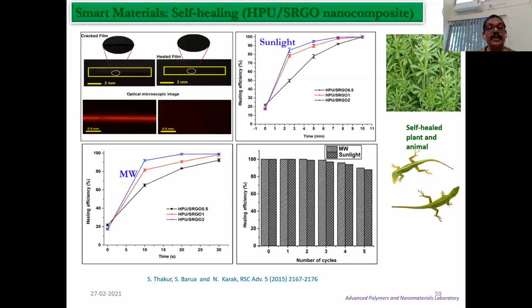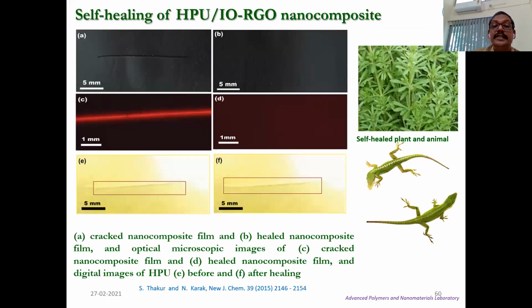But in our case, we have seen that you can get the self-healing character with high healing efficiency repeatedly without any additional self-healing agent, by the process that I'll show you, using microwave as well as sunlight as a non-contact trigger. This is possible even with iron oxide RGO nanocomposite based on bio-based hyperbranched polyurethane. And here you have seen that if the nanocomposite materials are not there, then self-healing is not possible to achieve.